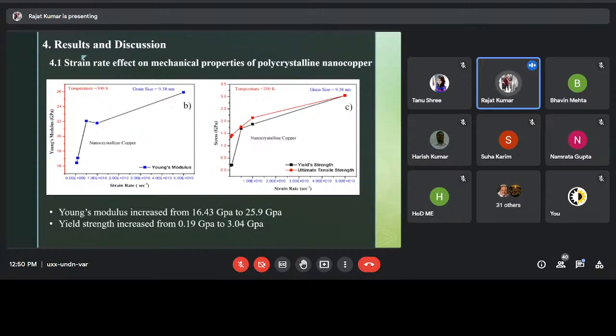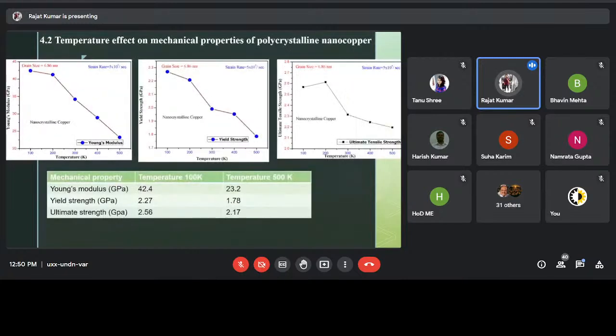So we can say that the mechanical properties are directly proportional to the strain rate. As we increase the strain rate, the metal shows higher properties. Contrary to the strain rate, when the temperature effect is observed, we found an interesting fact: in the case of strain rate, the properties increase directly with the strain rate, but in the case of temperature, the properties are almost inversely related to the temperature. For example, the Young's modulus was around 42.4 gigapascal at 100 Kelvin, and when the temperature is raised, it decreased to 23.2 gigapascal.